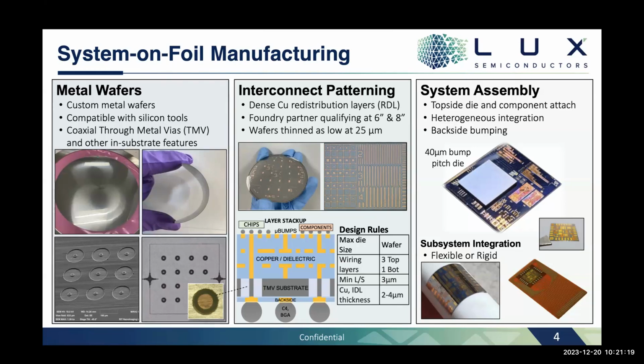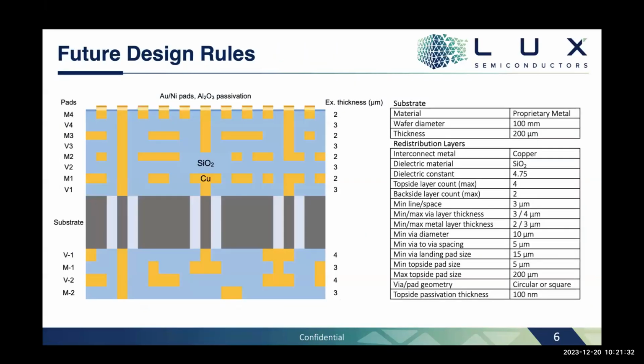I see. So it doesn't have to be symmetrical, is it? You're showing the interconnect layer on top, and then in the middle, you're showing some substrate layer, right? And below the substrate layer, it doesn't have to mirror what is on the top. It doesn't have to be a mirror. We just have to consider stress management, so we're not warping the substrate above a certain threshold. But it doesn't have to mirror it exactly. The metal that we use is relatively stiff, and so it is much more resistant to warpage than a silicon wafer would be at an equivalent thickness.